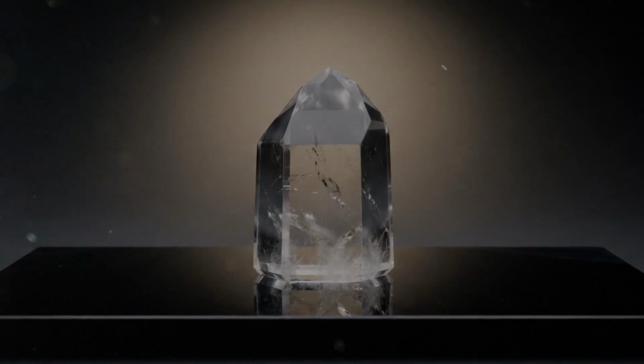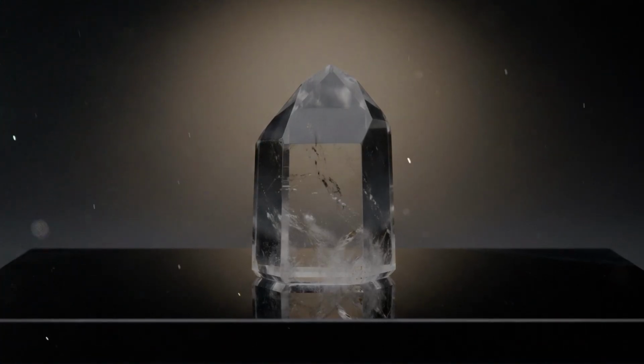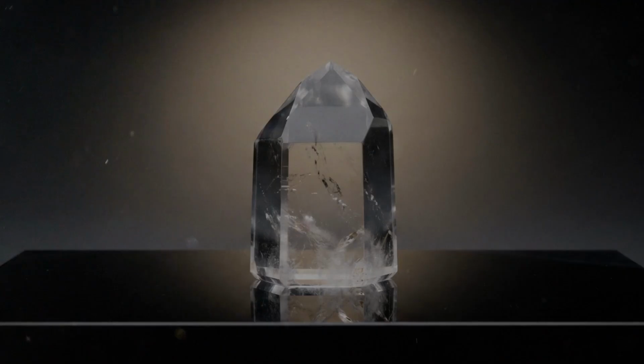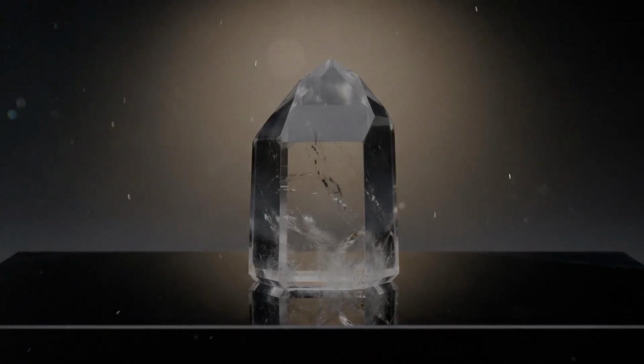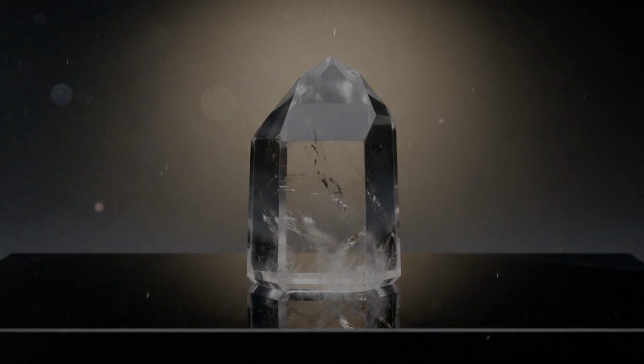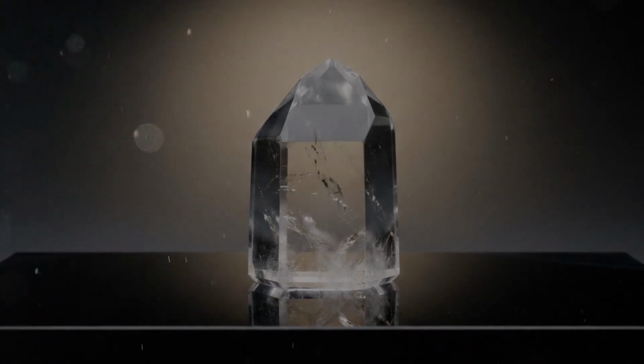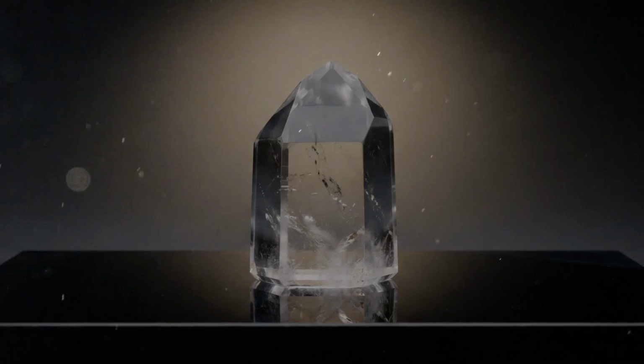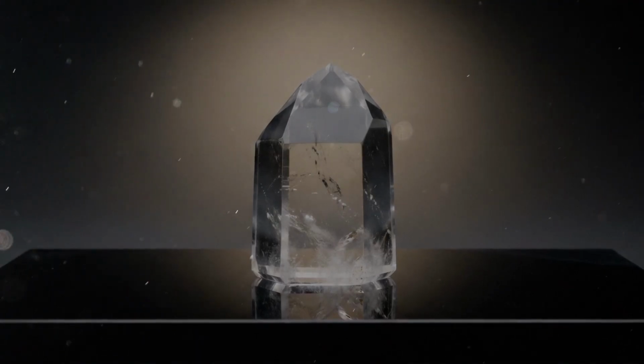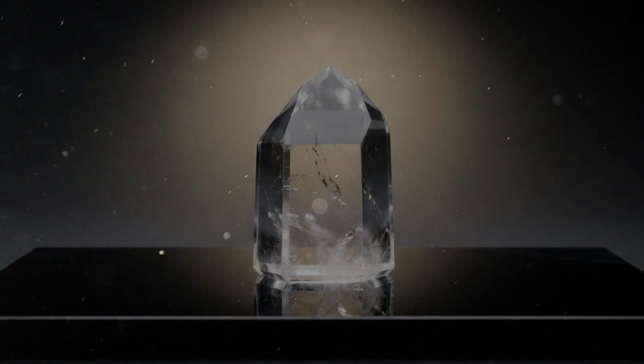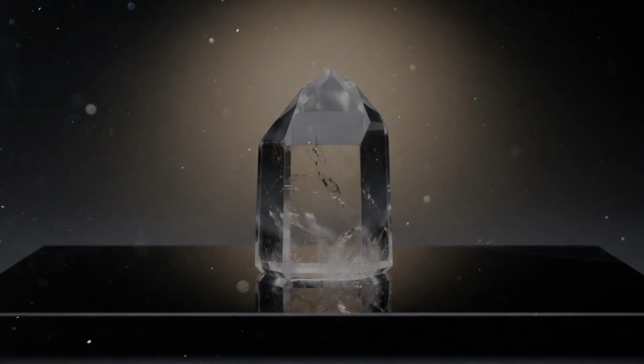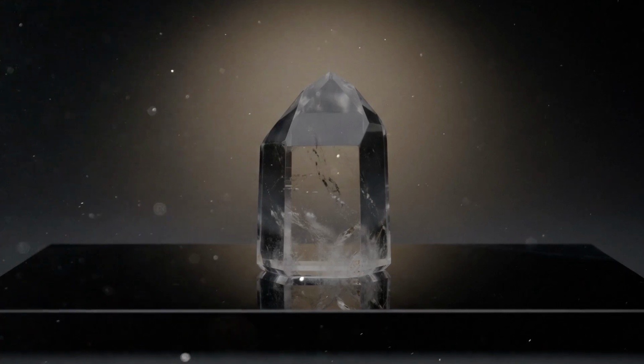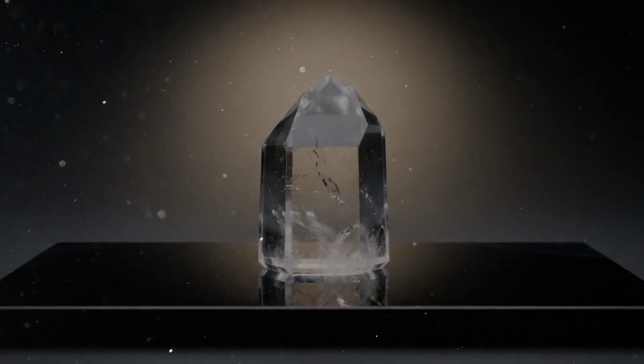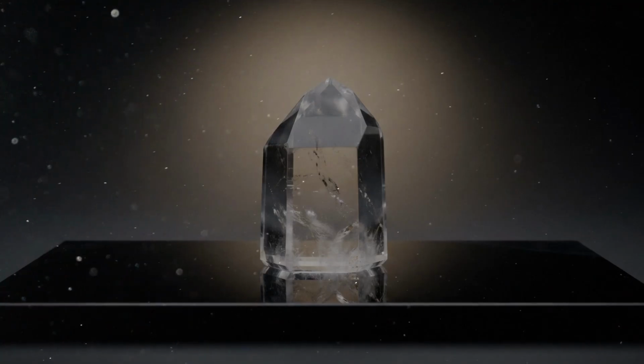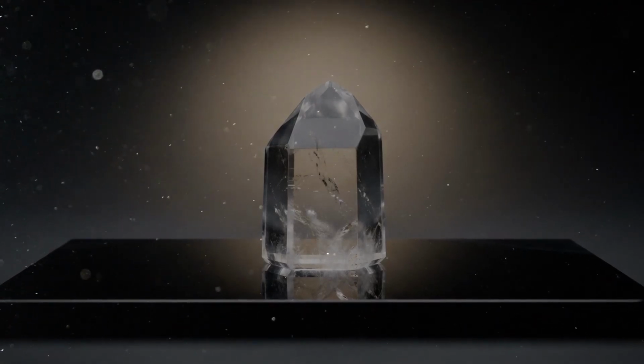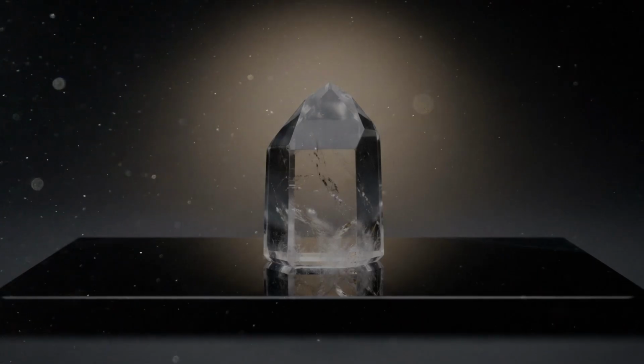Smoky quartz takes us back to radiation-induced color centers, but with a different mechanism than amethyst. Smoky quartz ranges from light gray-brown to nearly black, and this color forms when natural radiation affects aluminum impurities in the crystal. The radiation creates holes in the electron structure around aluminum ions, and these defects absorb light to create the smoky color. Very dark smoky quartz has special names. Nearly opaque black smoky quartz is called morion.